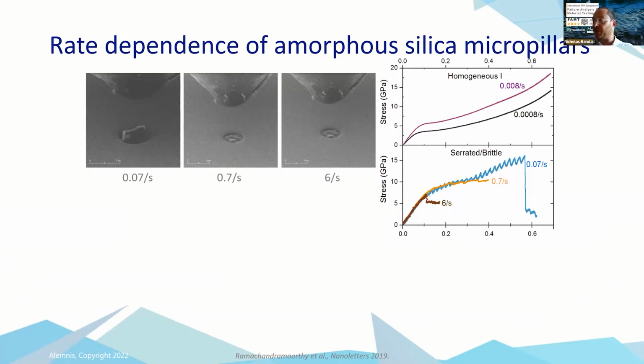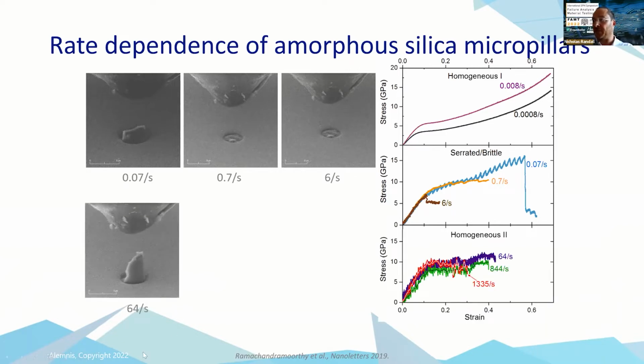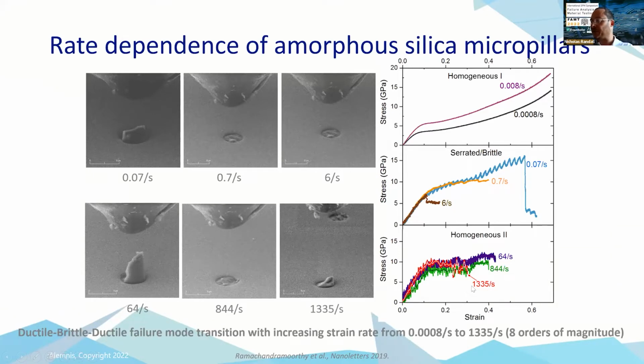But at the small scale, we see that at 64 per second, we're still brittle, but we see some ductility coming back. So this is the 64 per second, this is the 844 per second, and this is 1335 per second. So just on this slide, we've got 8 orders of magnitude of strain rate on the same material. And that really is new today, being able to look at the strain rate sensitivity, especially in semiconductor materials that might be subjected to high strains in service.